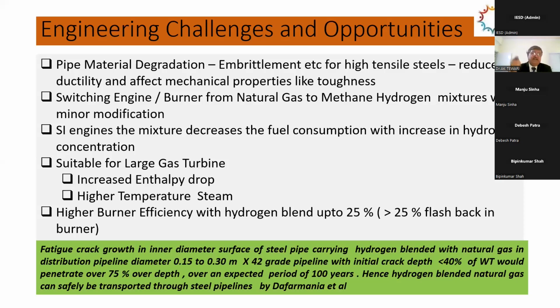The simulation study and fatigue testing analysis indicated that even after 100 years, the crack will not propagate beyond 75% of depth, from the already existing 40%. A pipeline is considered failed if it has 80% metal loss. So that indicates that, though the tendency of hydrogen for crack development is there, the crack propagation speed and other things are not so high. Next slide.